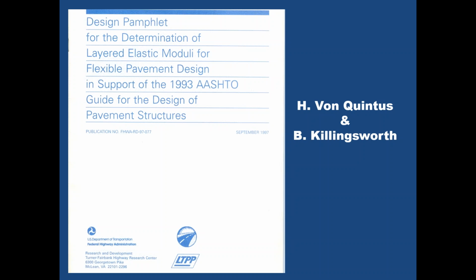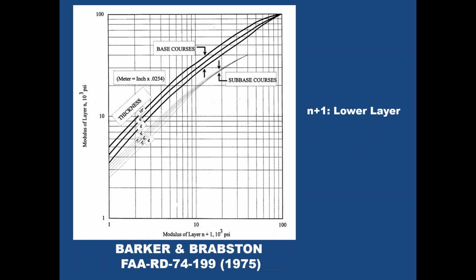So there was a taste of, quote, improvement from the standpoint of mechanistic empirical in the 86 and the 93 guide. This shows up in Harold's work, but it's actually based on FAA work by Walter Barker and Neil Brabston down at Waterways Experiment Station. And this suggests that the modulus of a layer is a function of the modulus of the layer beneath it, okay? So modulus of layer n plus 1, that's the lower layer, and then you move on up the line. If you know this modulus, you can estimate the modulus of the subbase and the base course for various thicknesses, okay? This is incorrect, folks. This doesn't work. This is not what controls the modulus of the granular material in a conventional flexible pavement, hot mix asphalt over granular base.